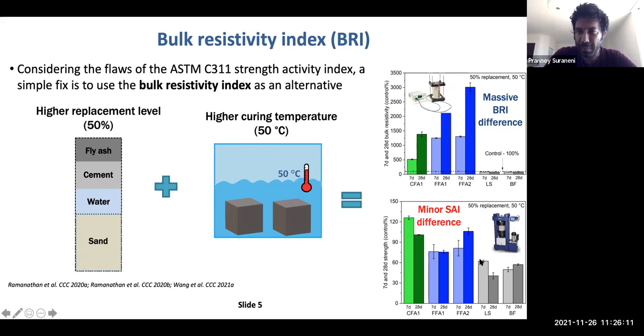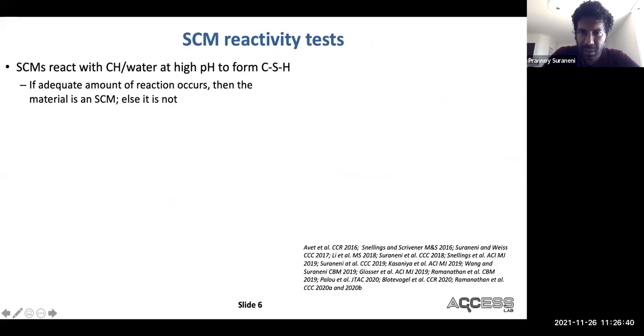On the other hand, for the bulk resistivity, which is far more sensitive to reactivity, the differences are astounding. The inert materials have the same bulk resistivity as that of the control, while the reactive materials have a value which is about 1,000% or 3,000% that of the control. So differentiation between reactive and inert materials becomes incredibly simple if you use the bulk resistivity index. I won't talk further about bulk resistivity, but if you're interested in it, please do let me know.